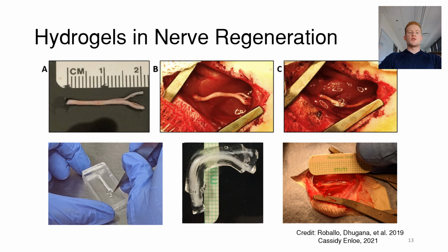Nerve regeneration is one specific area of tissue engineering where hydrogels are highly applicable. Previous methods involve squirting a glob of hydrogel solution into a surgical cavity and doing a bulk polymerization, as can be seen in these top figures. This crude process has given way to a more individual and personalized approach, where a scan is taken of the nerve and a specific mold is made to encase that nerve in hydrogel. This process only takes about 3 hours and can be seen here in these bottom figures.